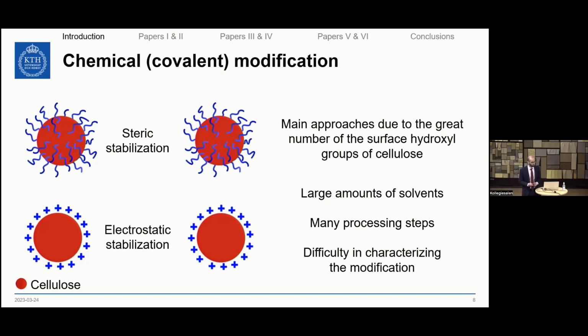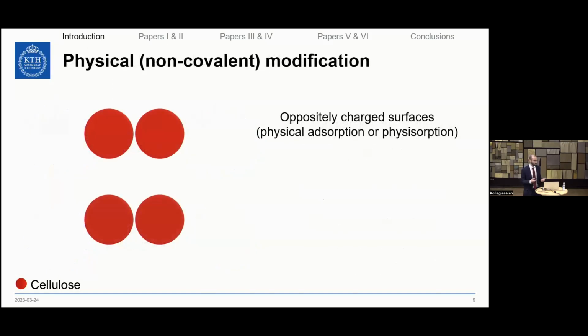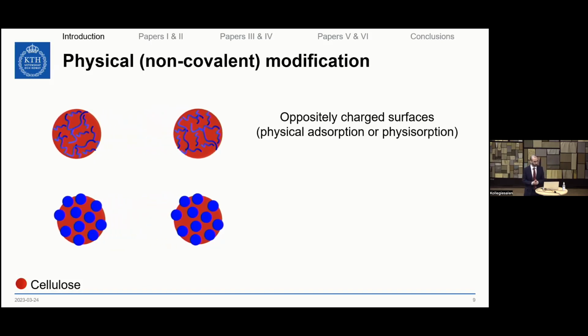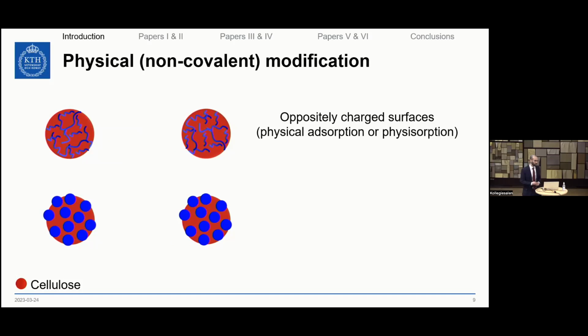These types of chemical modification techniques are applicable because of the great number of hydroxyl groups on the surface of cellulose. However, they require large amounts of solvents and many processing steps, and sometimes it is difficult to characterize the modification that was performed. So in order to bypass that, we can use physical or non-covalent modification approaches, where we can either have polymeric chains or polymer nanoparticles that are physically adsorbed onto cellulose, which will enhance the compatibility with other polymeric materials.